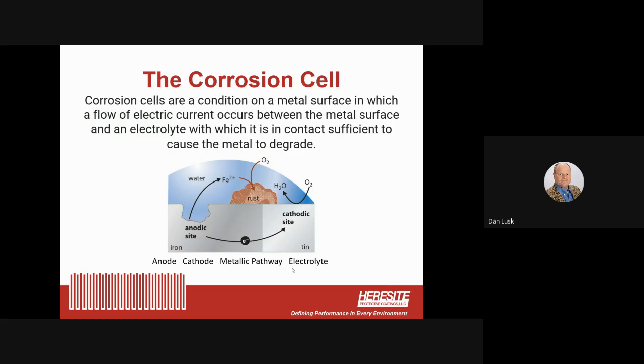So the basic thing that we try to prevent is the corrosion cell. It's a condition on a metal surface where an electric flow or a current occurs, and it's a degradation of the metal. So what we try to do is take one of four things away: either the anode, the cathode, the metallic pathway, or an electrolyte. If you take any of those four things away from a corrosion cell, the corrosion stops. And we eliminate the metallic pathway by keeping the electrolyte away from the metal by using a coating.